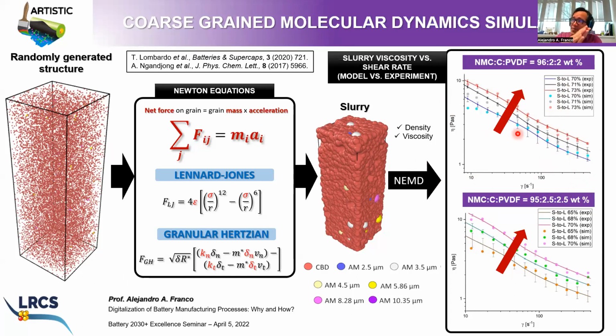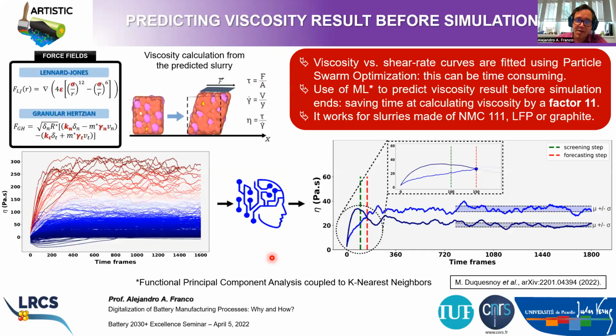Here, of course, in order to have this very good fitting, what we do is we fit the parameters, these 6 parameters which are represented here in red in the equations, in order to match perfectly all the conditions, right? In order to do so, we use optimization algorithms, okay? We use particle swarm optimization and machine learning. Just to give you a flavor of how we do this, we basically use this combination of a technique called functional principal component analysis and k-nearest neighbors, which is a kind of machine learning technique, in order to predict the result of this coarse grain molecular dynamics simulation before the simulation ends.